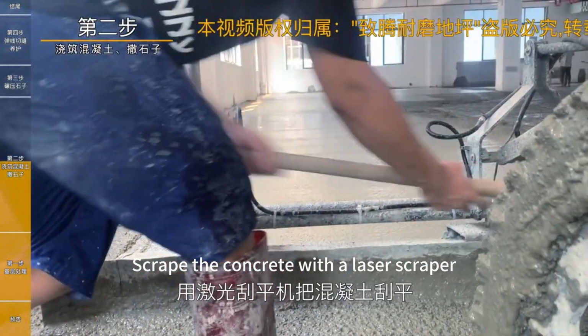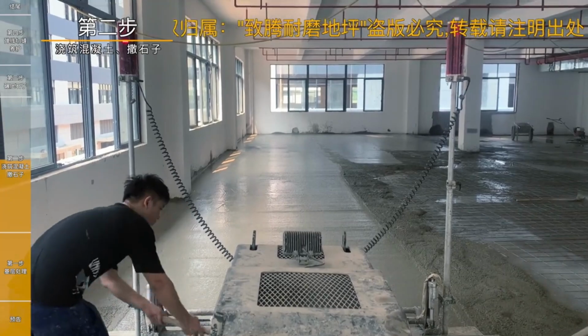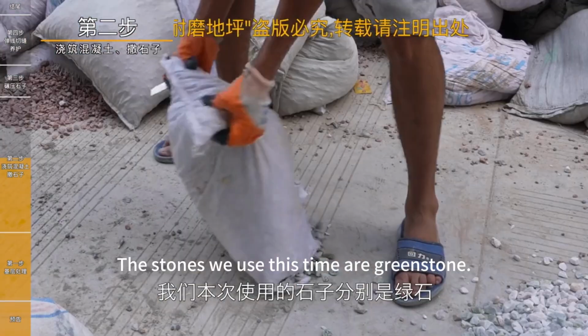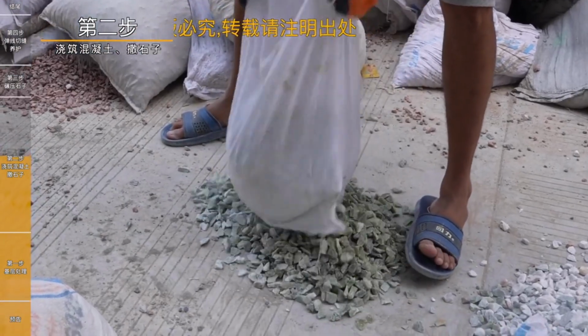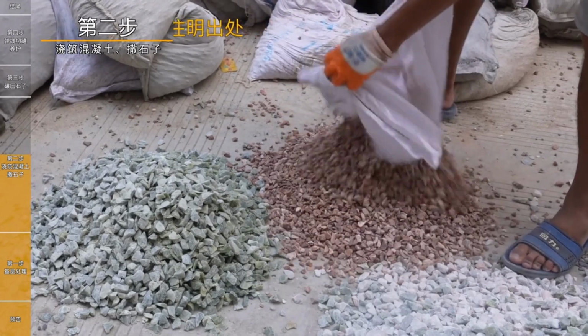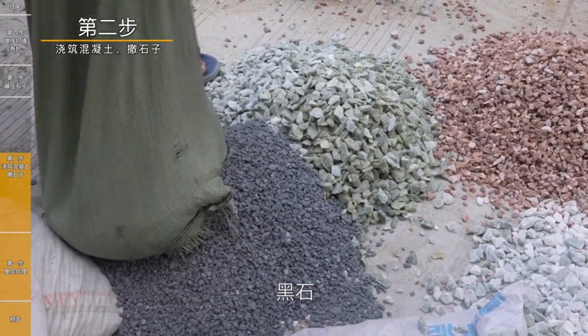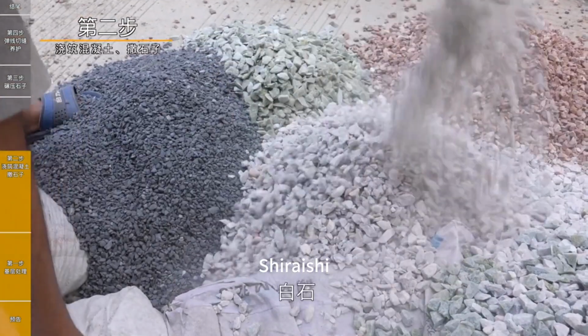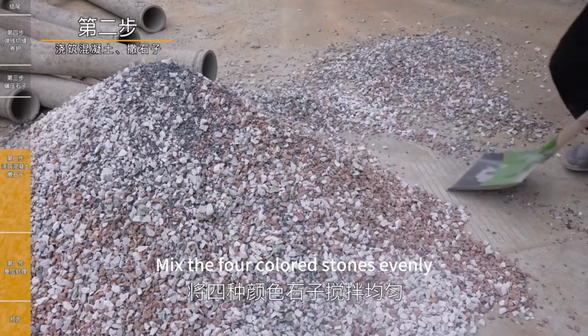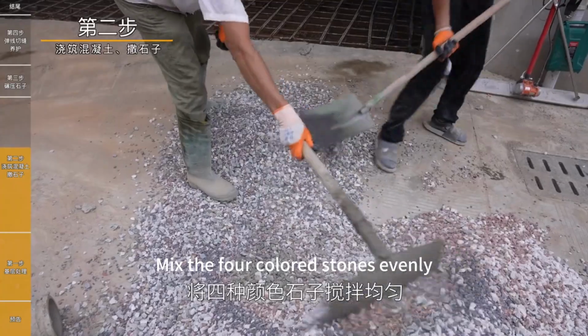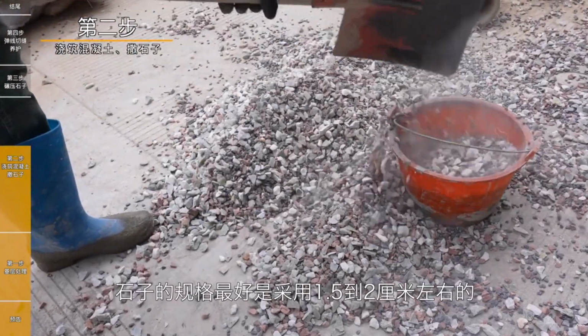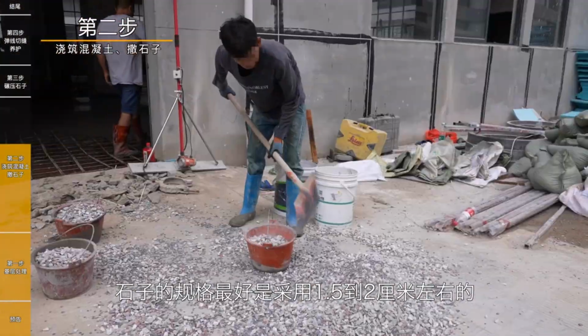Scrape the concrete with a laser screed. The stones we use this time are green stone, red stone, black stone, and white stone. Mix the four colored stones evenly. The size of the stone is preferably about 1.5 to 2 centimeters.